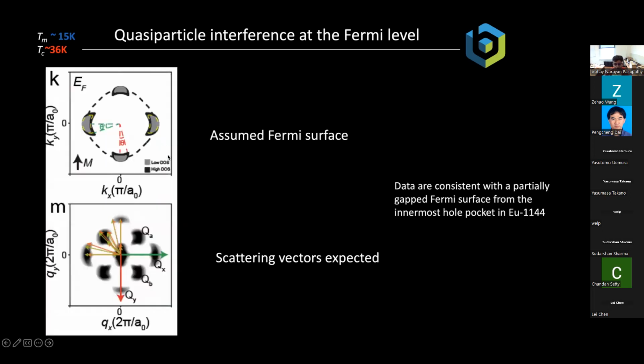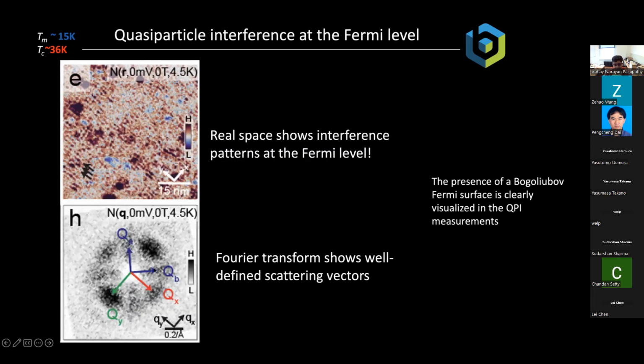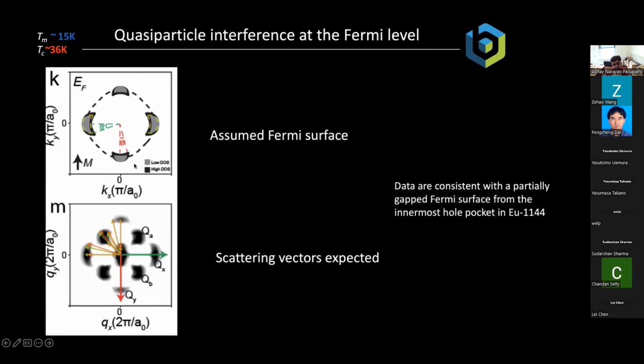Now, one thing we can do is we can take this kind of data of the scattering pattern, and we can try to guess what is the Fermi surface that gives rise to such a scattering pattern. And if you play this game, you'll realize, if you think about it a little while, that the Fermi surface that gives rise to the scattering pattern that we see in the experiment looks like this. And this data are consistent with a partially gapped Fermi surface from the innermost hole pocket of this particular material, for those of you who are interested in that.